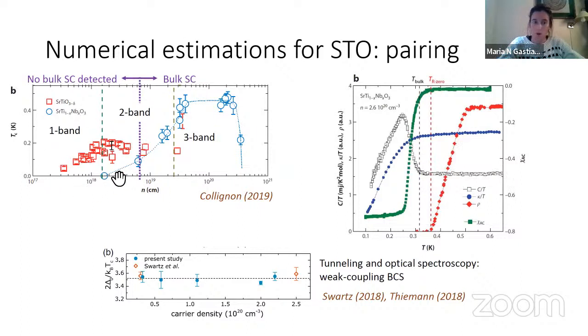What happens in this lower regime instead is that there are no bulk reports of superconductivity, but they do get very sharp resistivity drops. Another thing I would like to emphasize is that at least in this regime, there has been both tunneling and optical spectroscopy of the superconducting order parameter, and when they do 2 delta divided by TC, they get 3.5. So it's basically a better BCS material than aluminum. It's really the prototype weak-coupling BCS from these measurements.